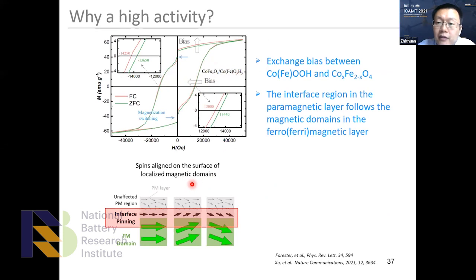So what is a pinning effect? This is actually a well-known effect in physics. Basically, we have a paramagnetic top layer and we have a ferromagnetic substrate. If we attach these two layers at an interface, this interface could be a few nanometers. At the interface, on the side of the paramagnetic material, the spins can be ordered. They follow the ferromagnetic domain over there. So it's pretty much like they become ferromagnetic, or they follow the ferromagnetic domain.